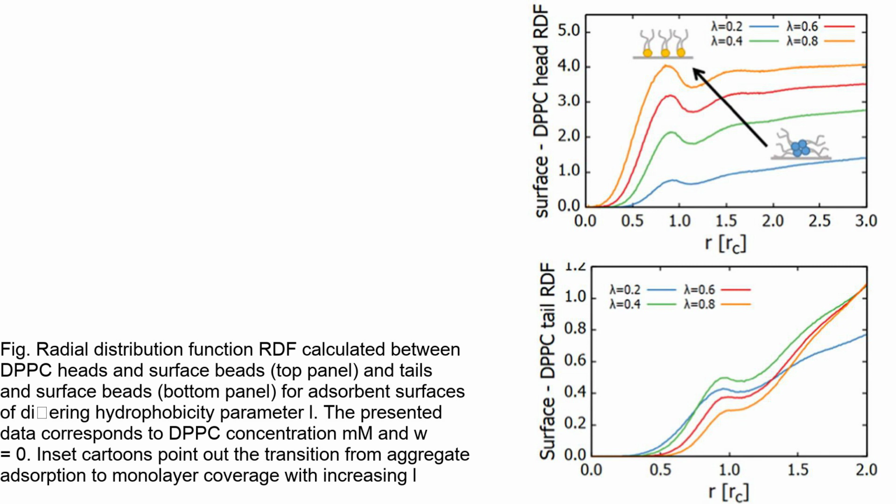On hydrophilic surfaces, the density of adsorbed DPPC increases with increasing DPPC concentration and surface hydrophilicity. This indicates the formation of a monolayer of DPPC on the surface. On hydrophobic surfaces, the density of adsorbed DPPC is lower and DPPC aggregates are observed. The aggregates are less strongly bound to the hydrophobic surface and may exhibit different geometries, such as spherical or elongated ellipsoids.